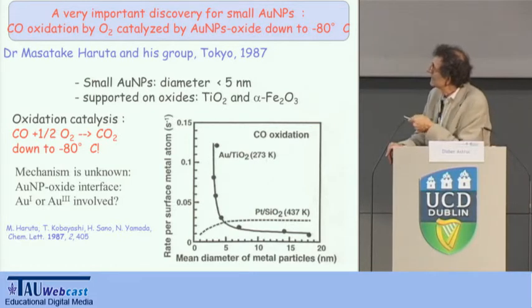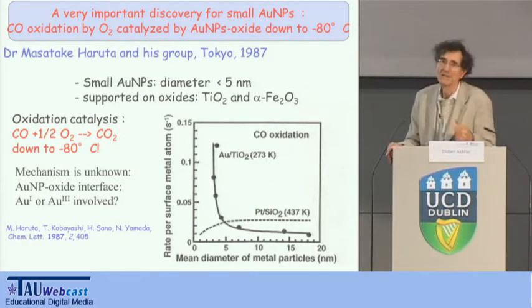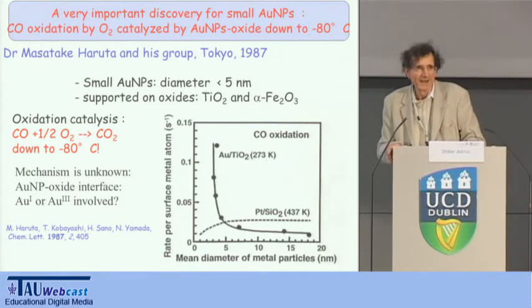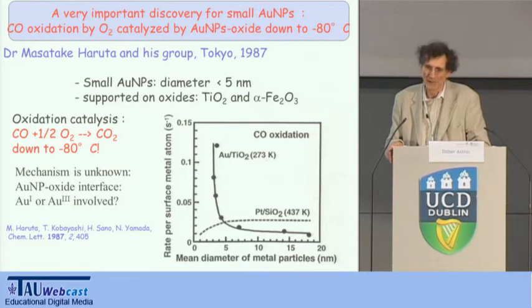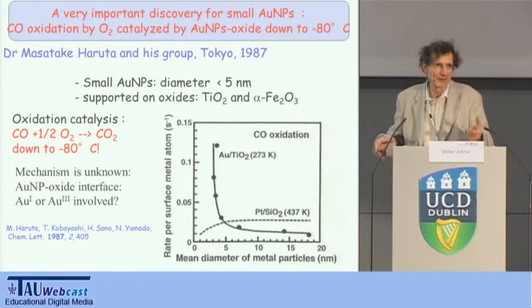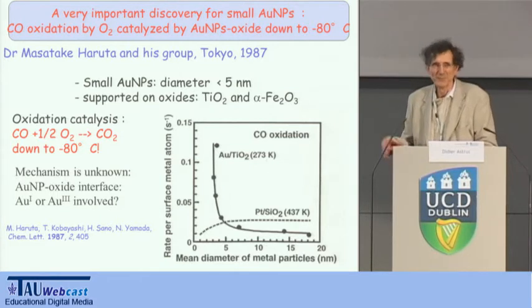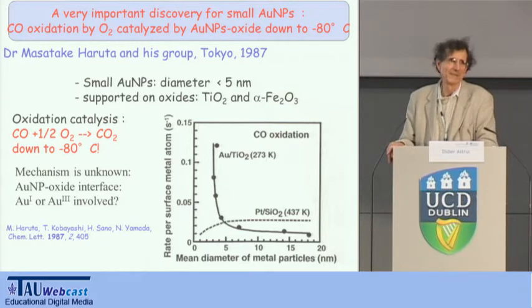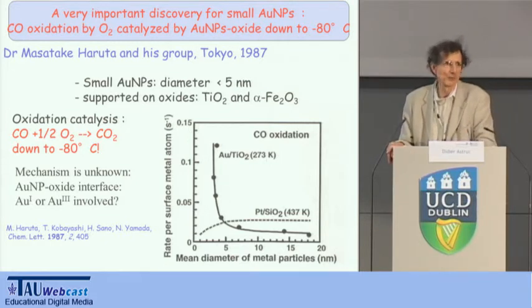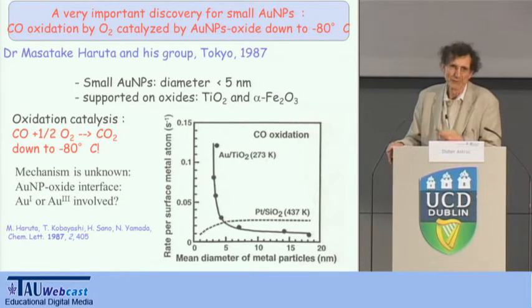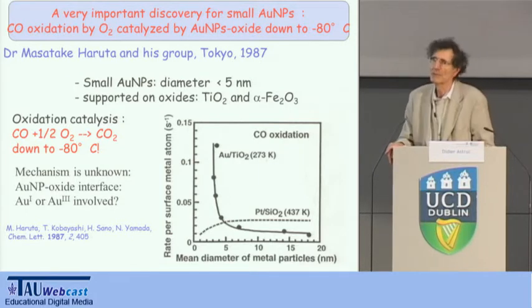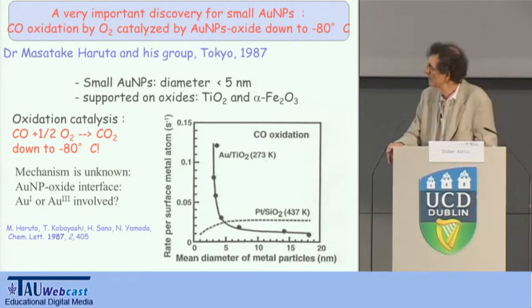So then this is able to oxidize CO to CO2, which means that if you start your car in the morning, normally you have platinum in your pipe, so the platinum will not be able to oxidize CO at room temperature. So in the first minute, you are polluting. But if you had gold nanoparticles in your pipe, then that would be oxidized immediately, even at low temperature, so you will not be polluting because you will have CO2 immediately. So anyway, this also tells that gold nanoparticles are extremely reactive, so one should be very careful about the potential production of gold 1 and gold 3, which are probably much more toxic than gold 0 nanoparticles.